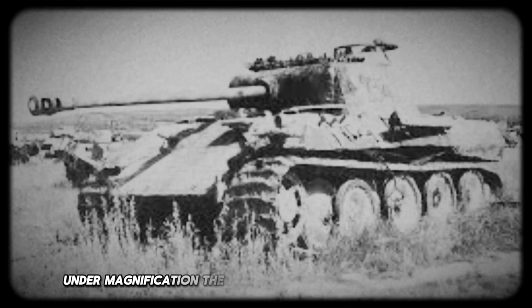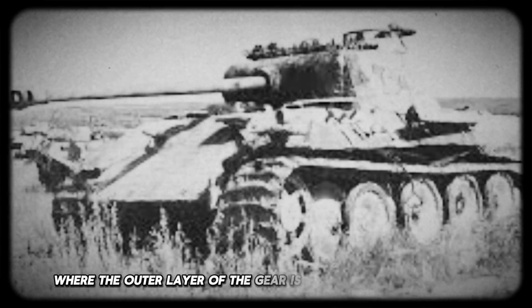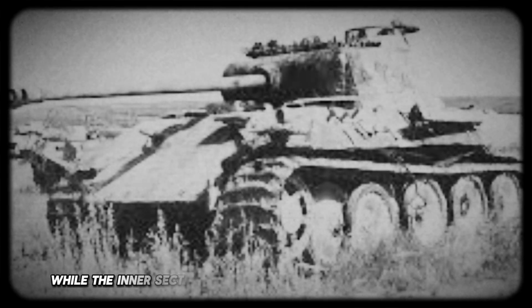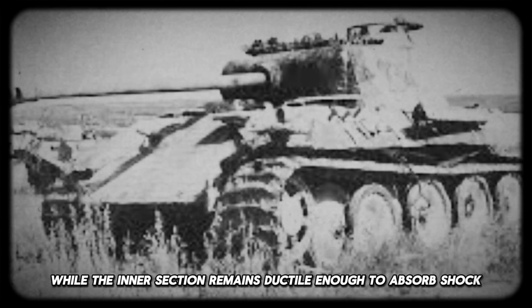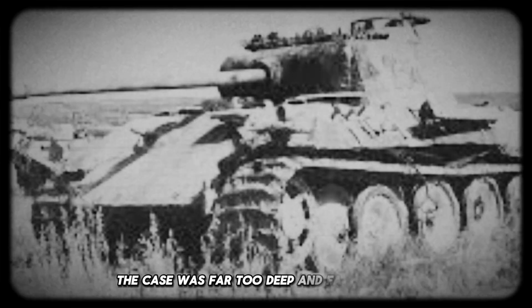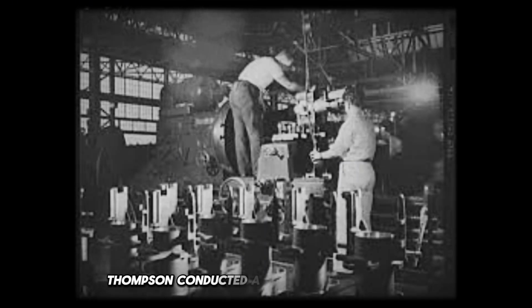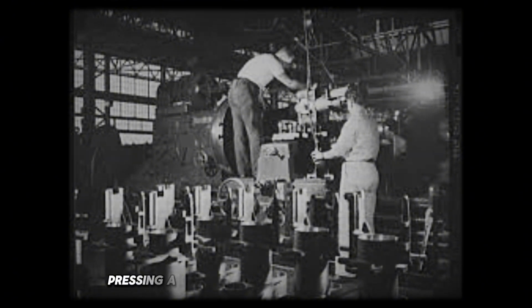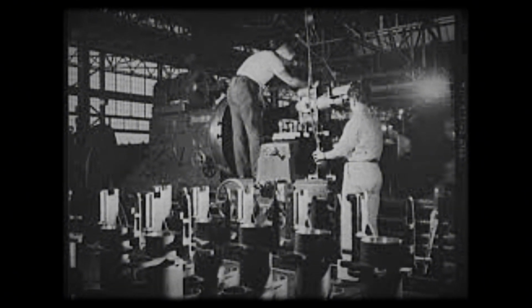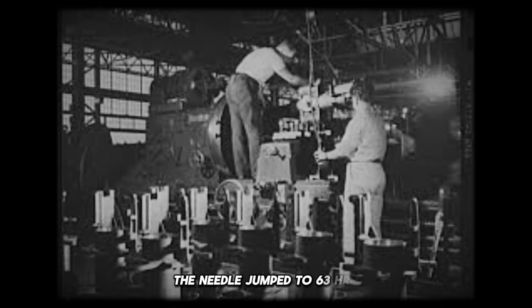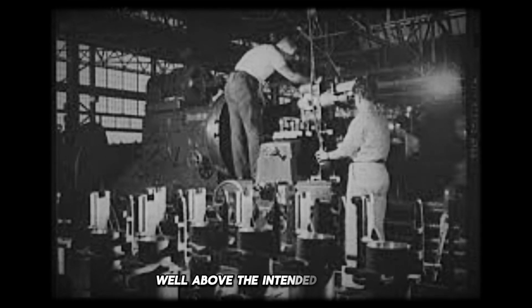Under magnification, the interior revealed a subtle contrast, harder steel at the surface, softer at the core. That part wasn't surprising. This was the result of case-hardening, a standard process where the outer layer of the gear is hardened to survive wear while the inner section remains ductile enough to absorb shock. But in the Panther's gear, the case was far too deep and far too hard. Thompson conducted a Rockwell hardness test, pressing a diamond cone into the steel surface. The needle jumped to 63 HRC, well above the intended 58 to 60.